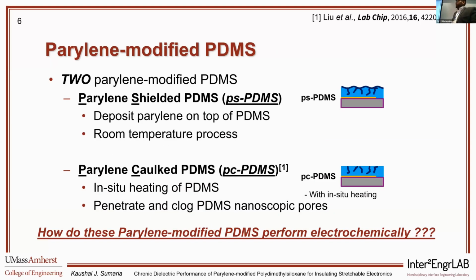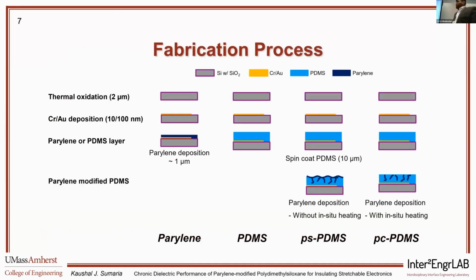ion-rich environment. So our fabrication process starts with a silicon oxide wafer, followed by deposition of chromium and gold layers. For the parylene deposition, we do a 1 micron parylene deposition. For the rest of the three samples, we start with a 10 micron spin-coated PDMS, and then followed by fabrication of room temperature parylene-shielded PDMS or a higher temperature parylene-caulked pc-PDMS. To maintain the uniformity, all three parylene depositions are done in the same session so that we know that the thickness of the parylene deposited is uniform.